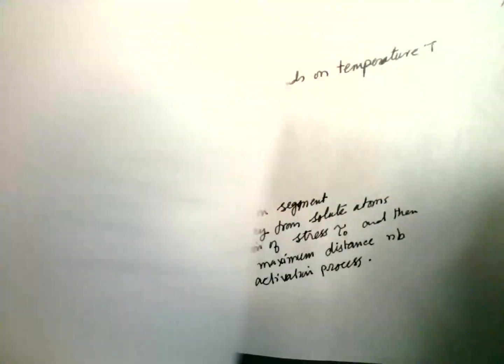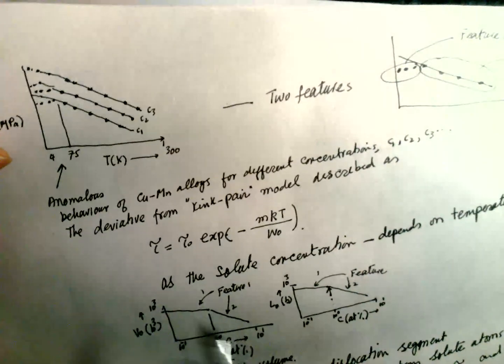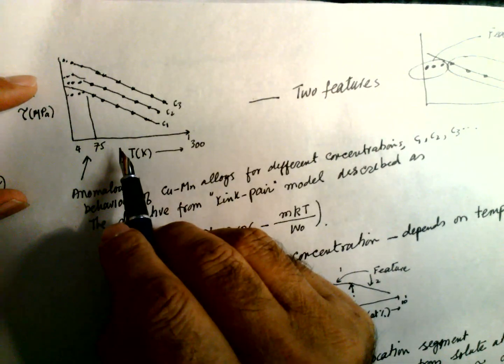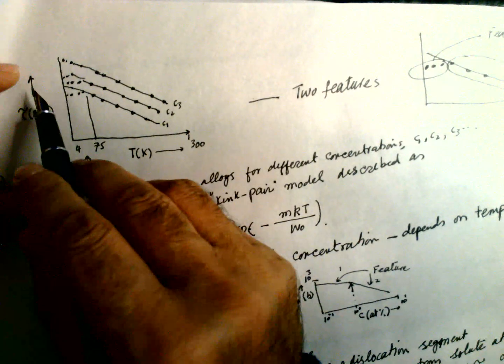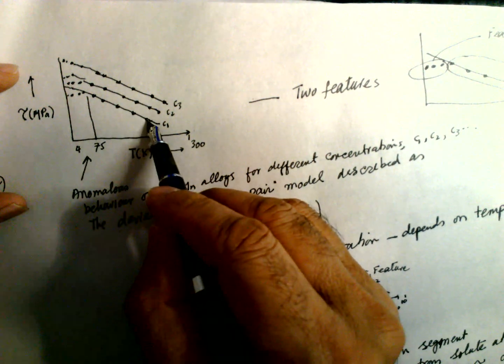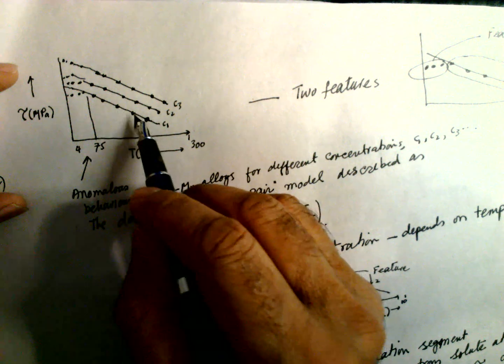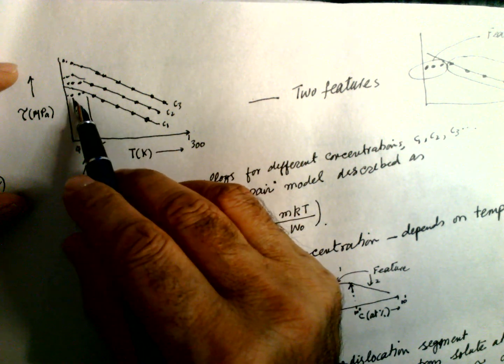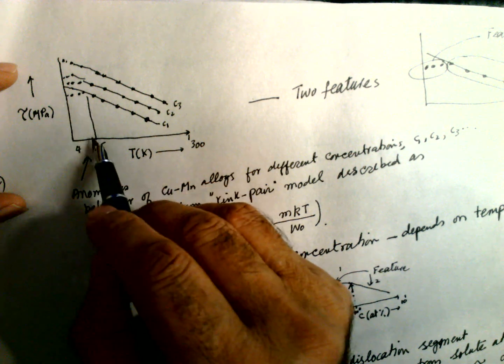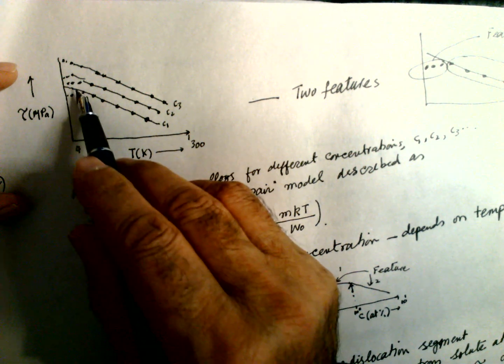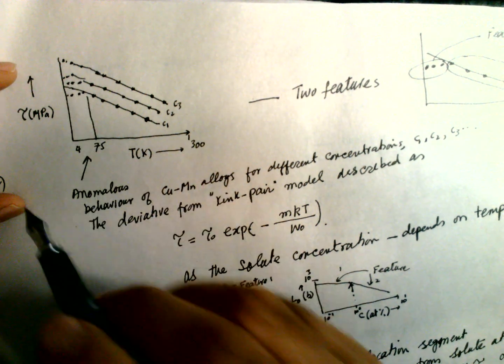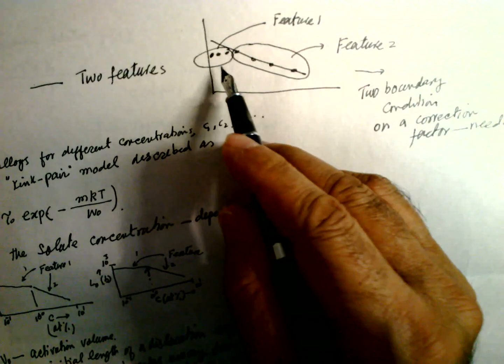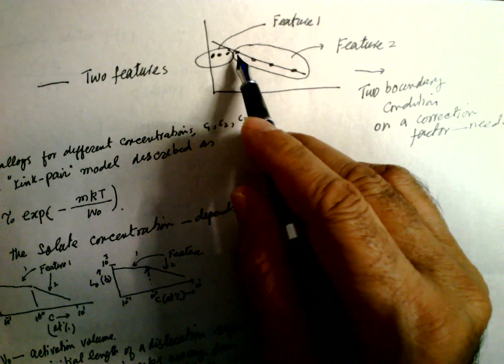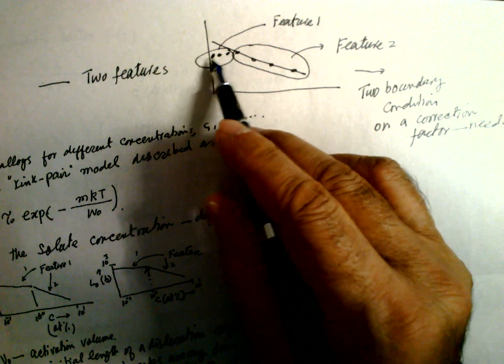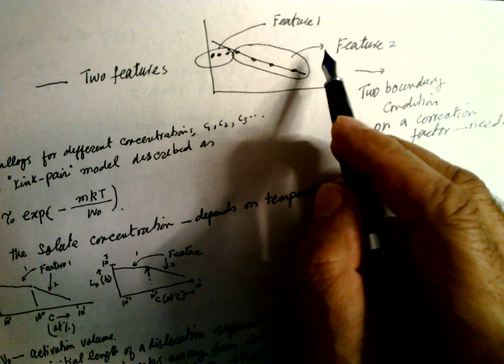This we have observed, which I discussed in my first paper of 1989. This is the stress, and this is the temperature, and the dots are the experimental points, and the line is the theoretical model. This model doesn't look good at low temperature below 75 Kelvin, so the line bends parallel to the x-axis. There are two features: one where the theory and the experiment match, and another where there is no agreement. So feature one and feature two.